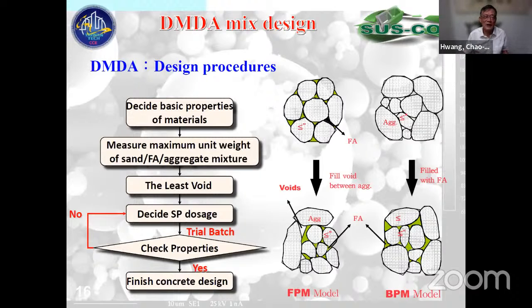So the system becomes very, very strong, okay, strong. Now we find that this void. And then we decide what kind of property we want. You want a durable concrete, you want the anti-corrosion concrete, or you want the ultra-high strength concrete. We design strength. So we use SP to aid workability, so make the concrete flow without segregation. So we have a very good durable concrete.